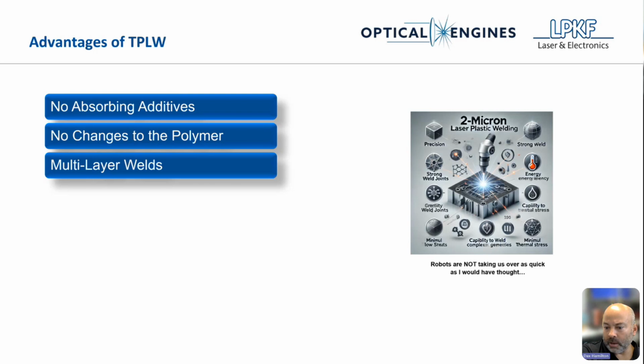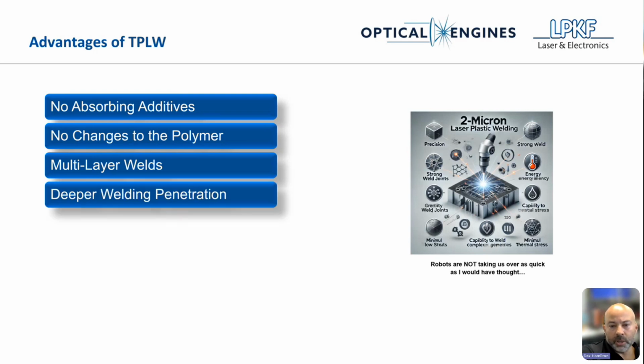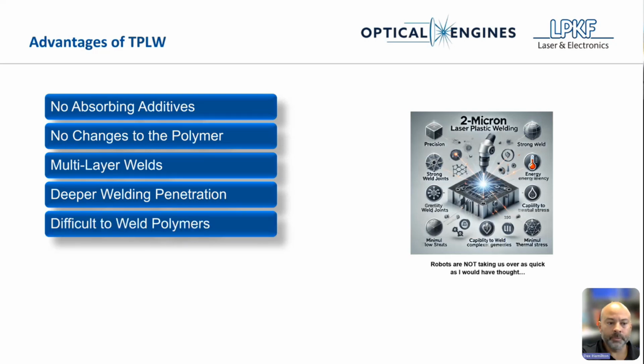So it's a good option to have for multiple layers. Deeper welding penetration. As I mentioned before, since typically the plastics absorb about 30% of the energy at 1940 nanometers, you can get the interaction, and again, it turns back to the volumetric absorption, where you can get this interaction all the way down through the plastics, therefore creating a deeper weld penetration.